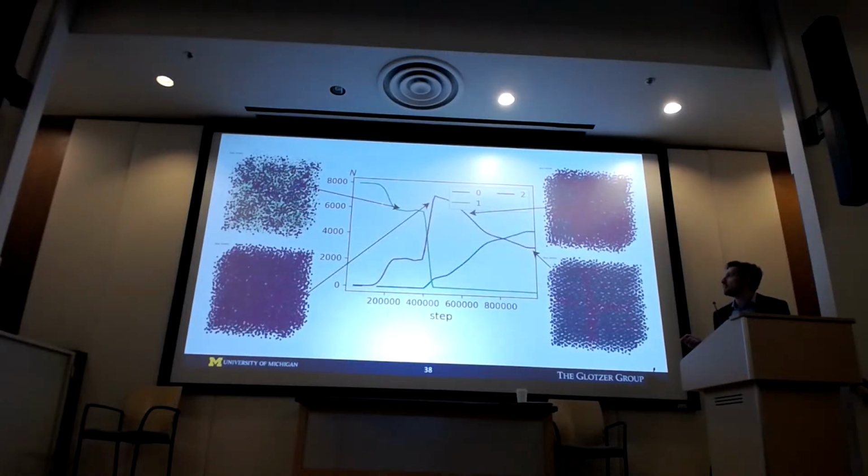We can show that there is some fluid environment at the beginning. Then we have this purple environment taking over after dropping the temperature at this step. And then eventually the system will have a higher concentration of these blue environments. You can see very nicely that this purple environment is essentially translating and forming into a crystal structure.